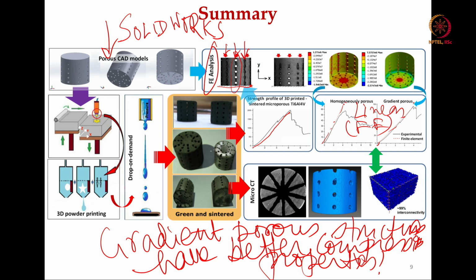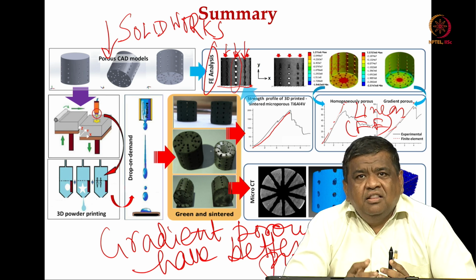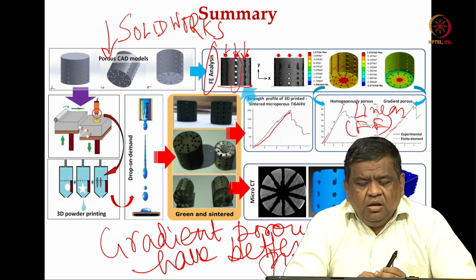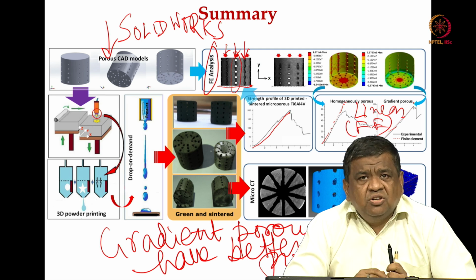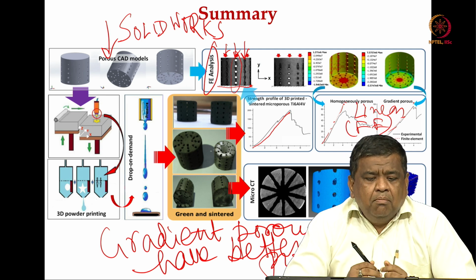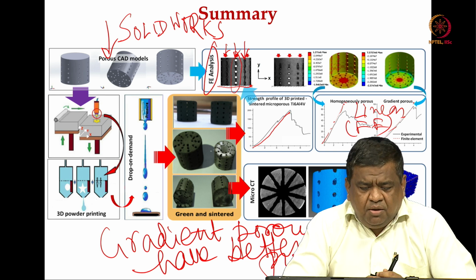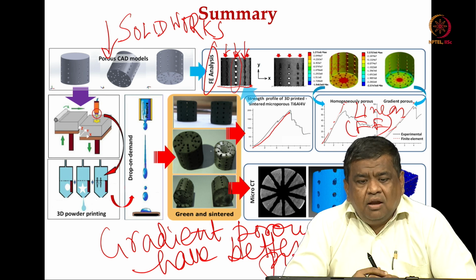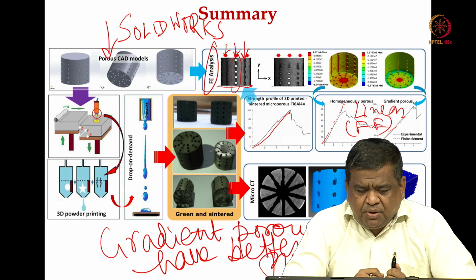Simply because when you do 3D printing and post processing, the material undergoes shrinkage and develops microporosity, which is an inherent disadvantage of these 3D printing based processes which you cannot avoid, and all those microstructural elements or defect elements cannot be captured a priori in the design file or CAD model. So, therefore, I repeat, microCT based 3D reconstructed images must be used as an input to the finite element model, and then only you can get very good correlation with the experimental results.